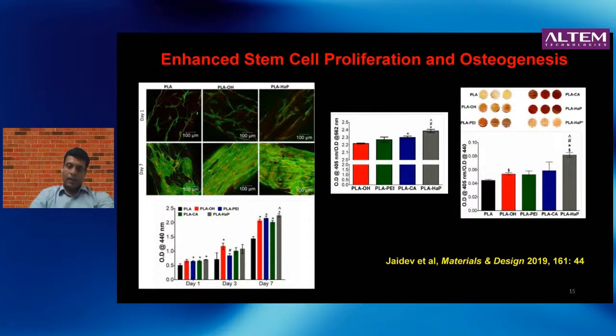There are several ways to look at it, but two ways we did was, one was to look at alkaline phosphatase. That's an enzyme that there's more of when the cells turn into bone-like cells. And the other is to look for calcium phosphate deposits that the cells will secrete, and that you can measure by staining it with a dye that is red in color. So you can see here that there's more alkaline phosphatase expression on scaffolds that had the hydroxyapatite coating compared to all these other scaffolds which did not have that or only had these other coatings.